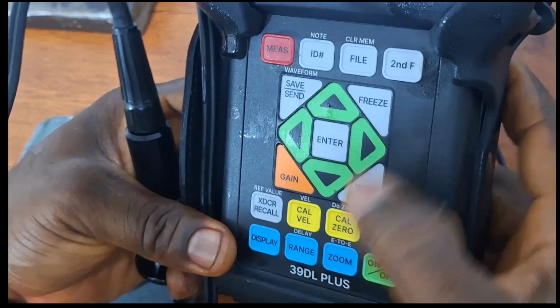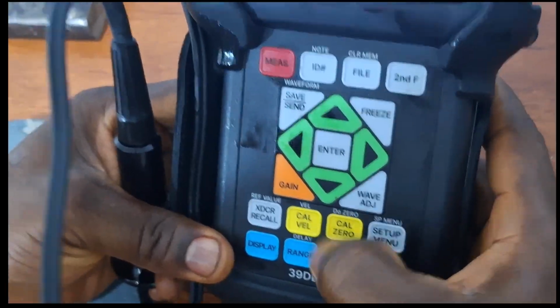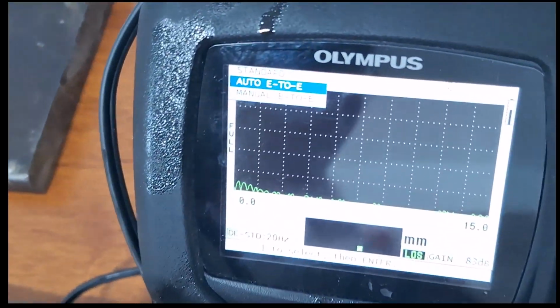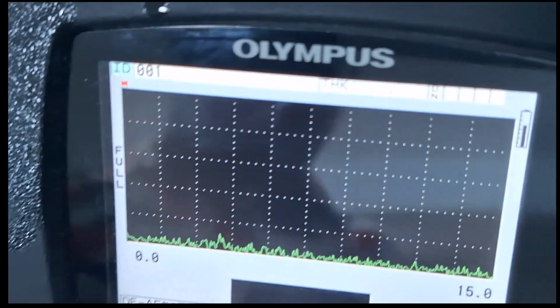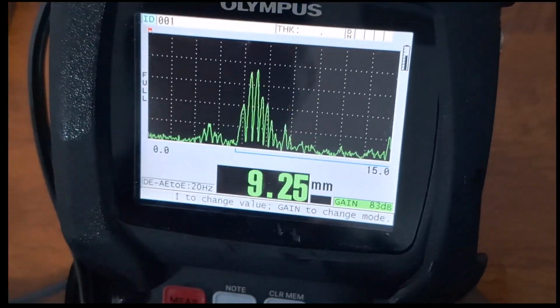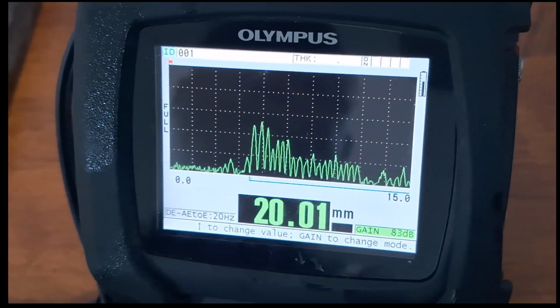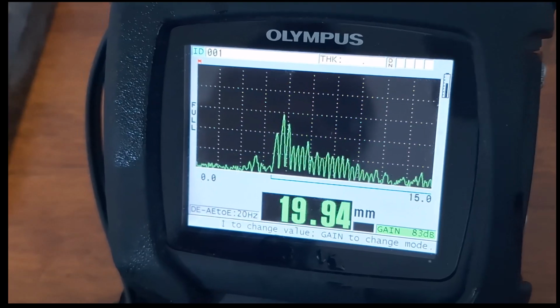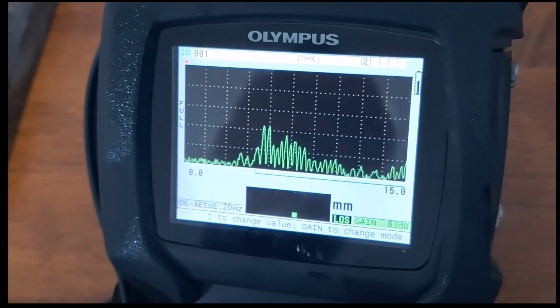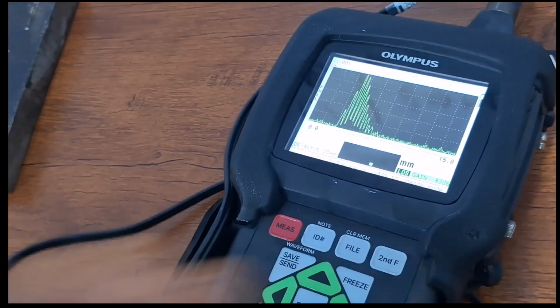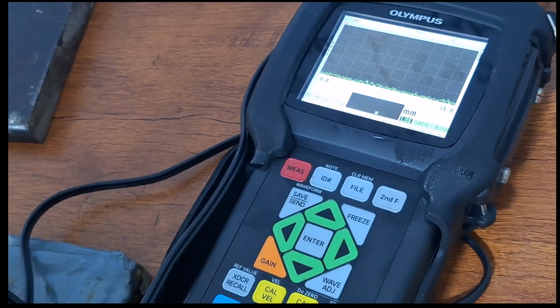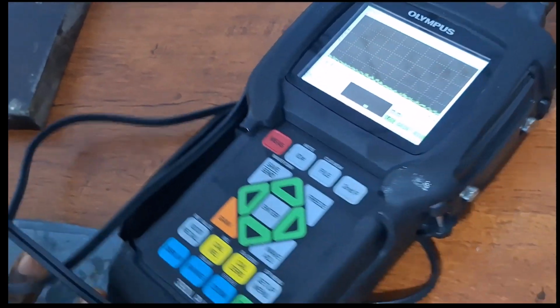But if I come back to my second function and pick the option and I take my auto echo to echo, so we are now in the echo to echo mode. If I take my reading, you can see now the same area I'm getting 19.9, which is approximately 20 mm. So the machine automatically recognizes that there is a coating and it has subtracted the thickness of the coating.